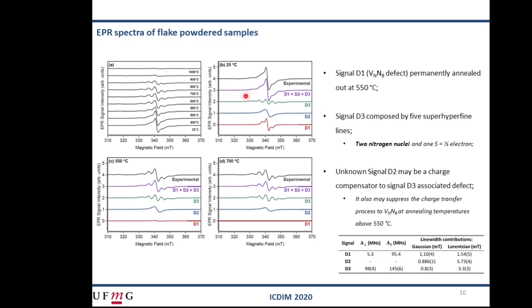So the signal D3 is composed of 5 EPR lines necessary to explain the experimental data. The simplest way to implement this third signal was to admit that it is formed when two nitrogen nuclei are interacting with an electron. In an EPR experiment, this is described by a super hyperfine interaction that is illustrated by a spectrum formed by 5 lines showing an intensity ratio of 1:2:3:2:1. That is, the central line here, here, and here is 3 times more intense than the first and the last lines.